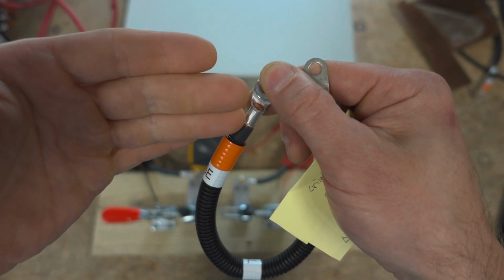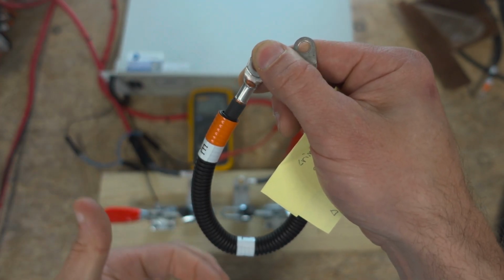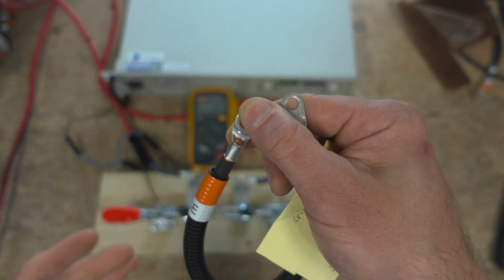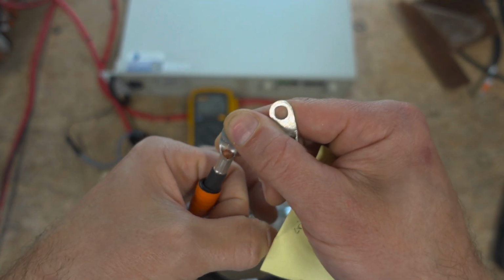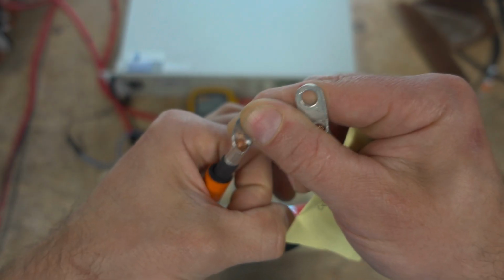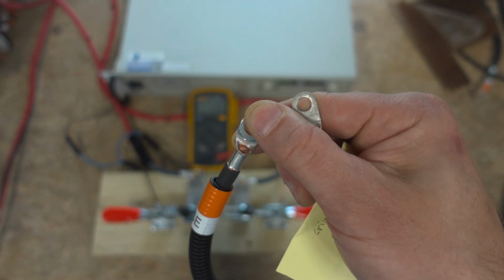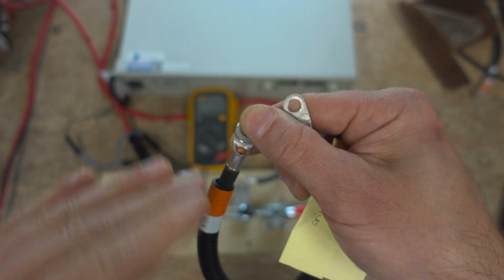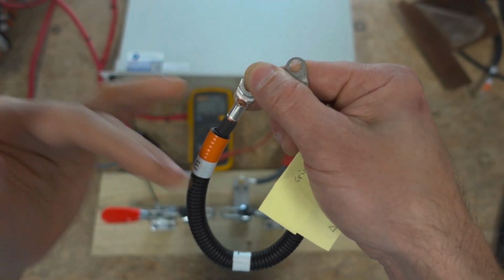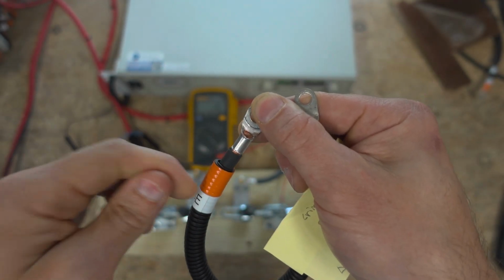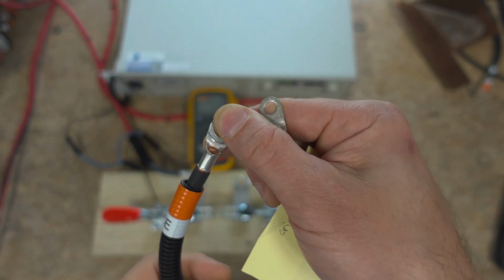And of course, the embrittlement you get when that solder wicks down here isn't worth the trade-off. And again, localized mechanical strain relief that's only preventing you from moving slightly is not a solution to prevent the embrittlement from causing fracture, from causing a fatigue failure inside of this copper, wherever that copper ends.